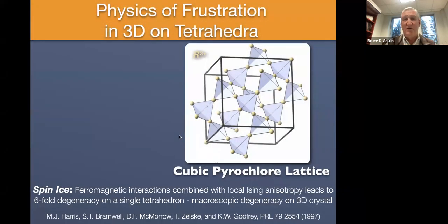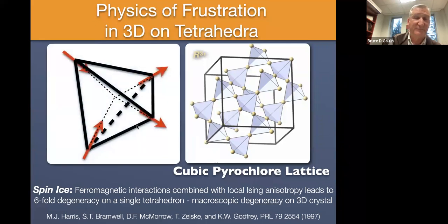Right. So anyway, I'm going to jump right in to a case study of a particular geometrically frustrated magnet. It's going to be a magnet based on this structure that you can see over here on the right-hand side. It's referred to as a cubic pyrochlore lattice. The underlying architecture with which we're going to decorate this lattice is that of corner-sharing tetrahedra. The significance of the tetrahedra, this is one tetrahedron: we're going to put magnetic dipole moments at the four vertices of a single tetrahedron, and then imagine, for different combinations of single ion anisotropy and interactions between the moments, how we can minimize the energy of the system.